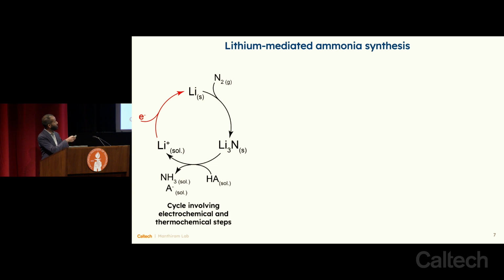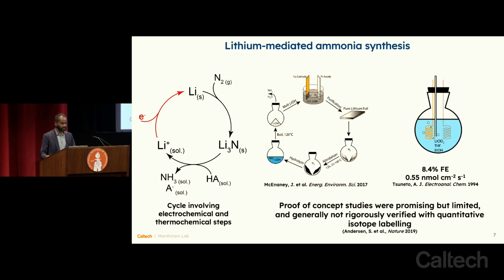That in turn leads to exchange of the lithium ions with protons. That in turn makes ammonia as a product, with lithium ions discharged into solution, and those lithium ions can then be plated so that we return to lithium metal and can continue around this cycle. So there have actually been a few demonstrations of this.